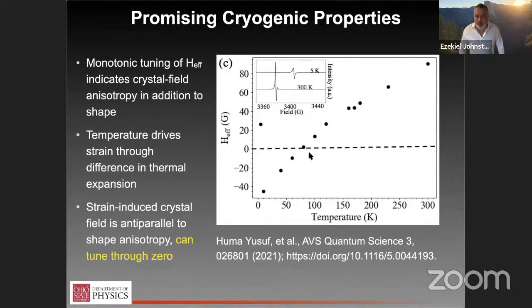And this tuning through zero does two things for us. First, it actually provides additional insight into the structure, in that it suggests there's a crystal field anisotropy that's been hiding for the last 15 years in this system because it happens to be pointed anti-parallel to the shape anisotropy. So all of the systematics that one would do to look for an anisotropy field can't distinguish between those two contributions. That's why we label this H effective rather than M effective or M sub S. So that's interesting from a fundamental science point of view. From an applications point of view, this points out that using this strain tuning, we can not just modulate the magnetic resonance frequency, we can tune into a zero anisotropy regime, which is very interesting for looking at sort of more exotic magnetic resonance tricks that we might want to play.